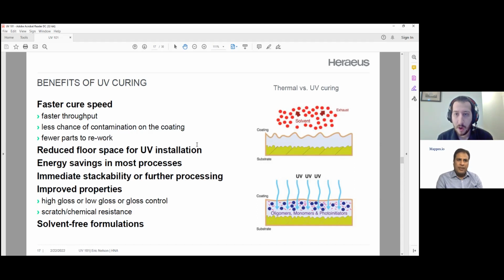Nice. In terms of curing speeds, what is the comparison? Like if somebody was using an oven versus somebody using UV, is there... Yeah, it really depends on the UV chemistry. I'd say there's a pretty wide range of conditions that would affect drying time or curing time. Often the coating thickness plays a large role. So if you have a thick coating, it takes a much longer time for it to be evaporated off to dry. Or likewise, it might take more energy to penetrate deeper into the thick material.